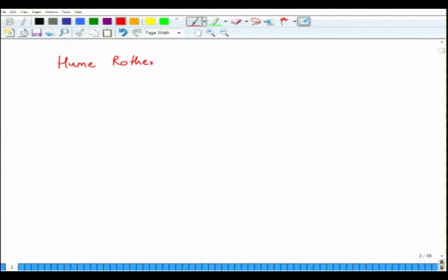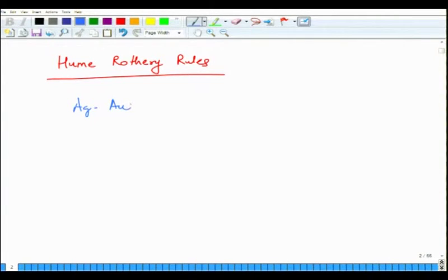There are some rules for substitutional solid solutions, which are called the Hume-Rothery rules. They say that it depends upon the size difference and the valence difference. If you want to make a substitutional solid solution, extensive solid solubility is permitted only when the size difference is less than 15%, the valences are similar, the crystal structures are similar, and the electronegativity difference is very small. There are certain violations, but by and large these rules are followed. The examples we took were gold, silver, silicon, germanium, and copper, nickel. These are solid solutions basically.